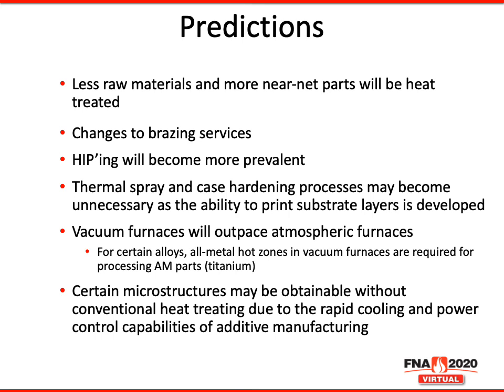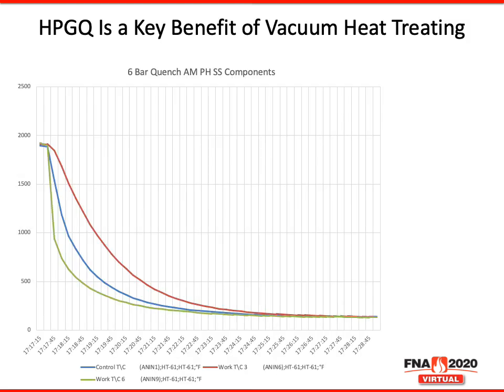Wanted to make note that in a HIP furnace, parts are heated at a high temperature and are cooled slowly. However, with a vacuum furnace and high pressure gas quenching, it's a key benefit to vacuum heat treating, as you can quench at significantly higher pressures and quicker velocities to get full metallurgical structures as quenched.